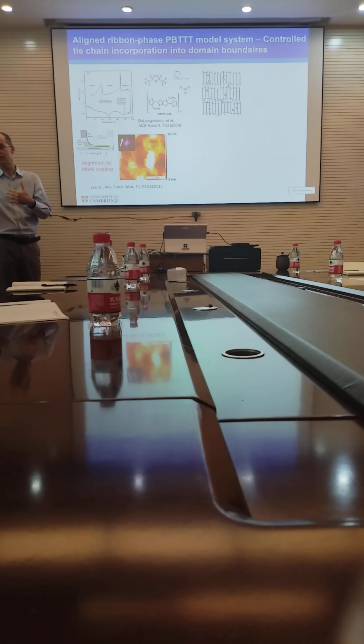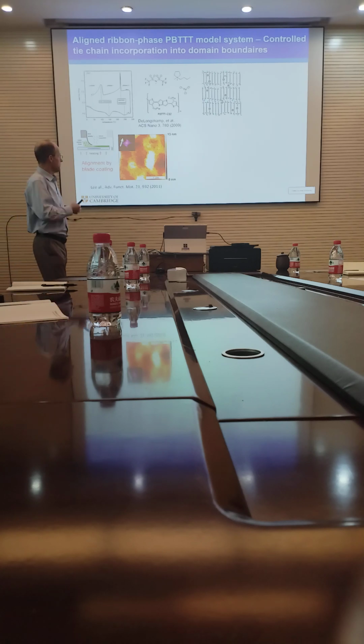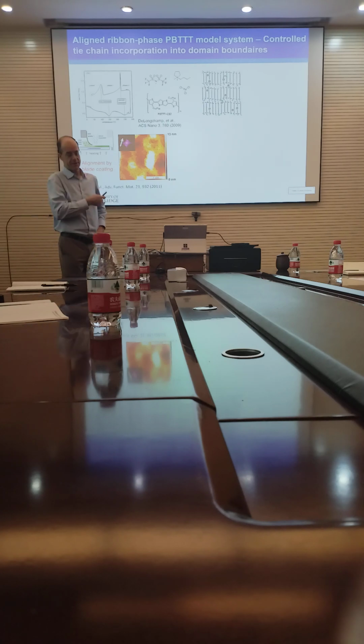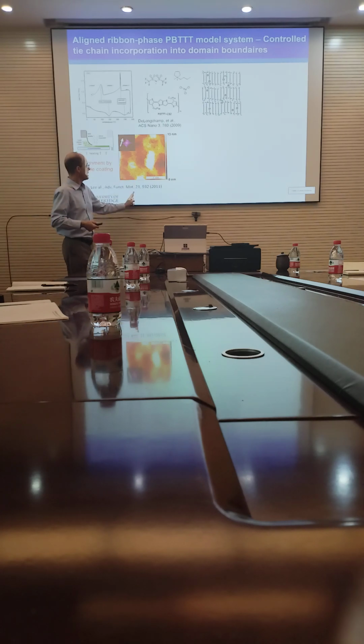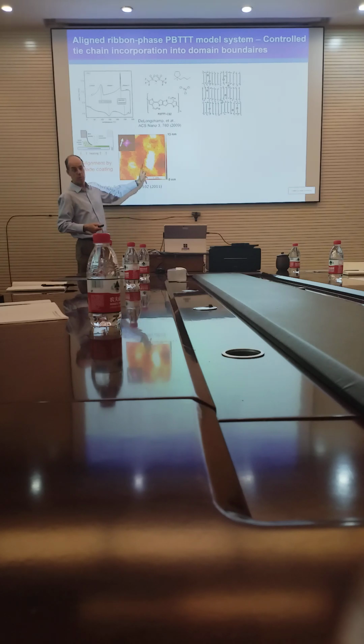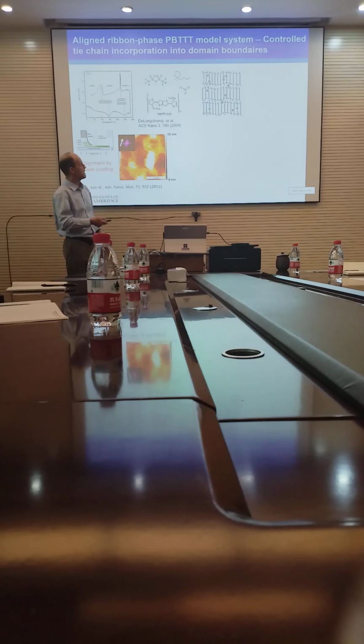And so in this system, we thought this is a system where the transport, if you measure the electrical conductivity in this direction, so that means along the polymer chain direction, the conductivity is strongly limited by these domain boundaries. Every 60 nanometers, you hit one of those domain boundaries, and then the charge has to hop from one chain to the next within one of those domain boundaries. That's the rate limiting step for the conductivity in a system like this.